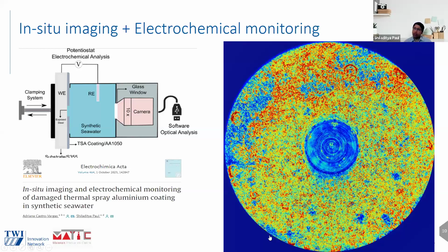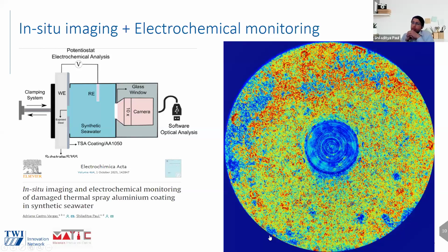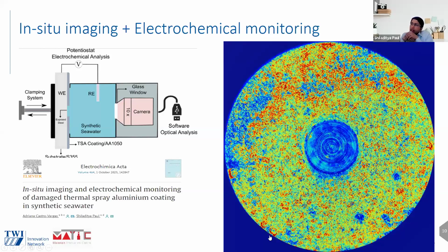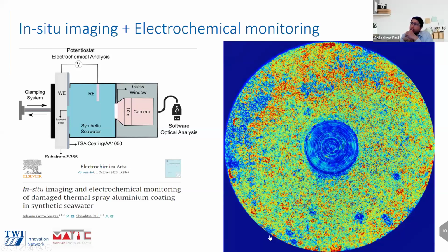So we used in situ imaging and electrochemical monitoring to understand how the activity when you have a defect within the coating. So in the middle, you see there is a defect. So that defect is the steel substrate, and the rest of that circular region you can see on the outside, the ring, is actually thermally sprayed aluminium.